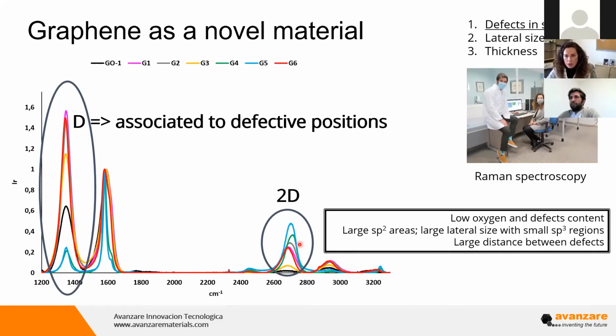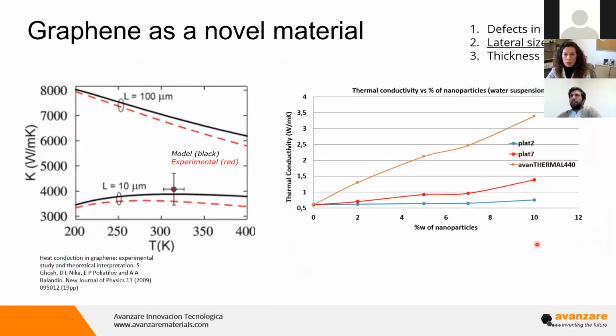But in summary, we need to have a graphene with low oxygen, because oxygen is the main defect present, linked with the carbon. So we need to have low oxygen and defect content. We need to have sp2 areas as large as possible with small sp3 domains, and with a large distance between the defects, so that in these large sp2 parts, the electrons, and in this case the phonons, can move easily. The second feature that I need to highlight is the lateral size of the material, both in modeling and experiments.